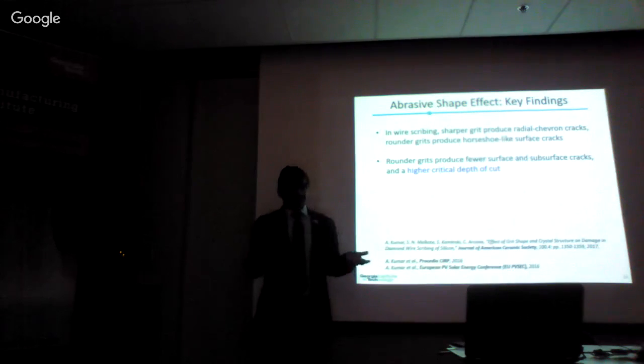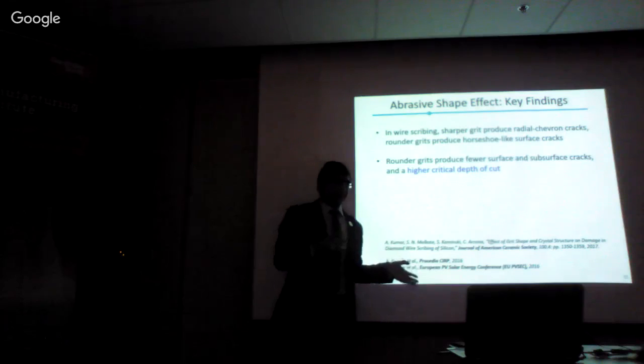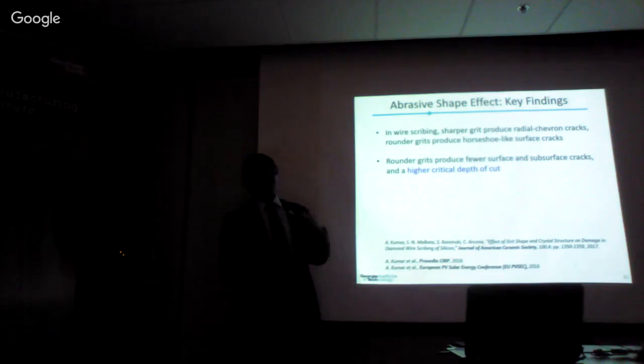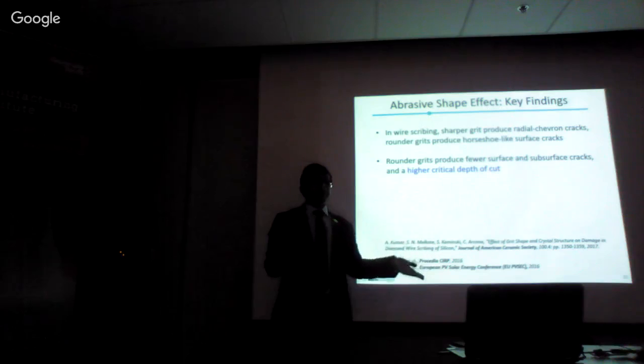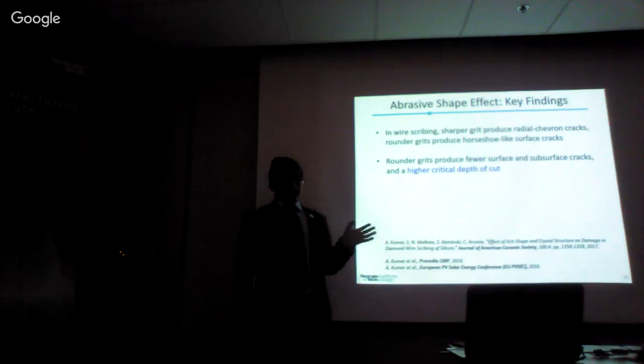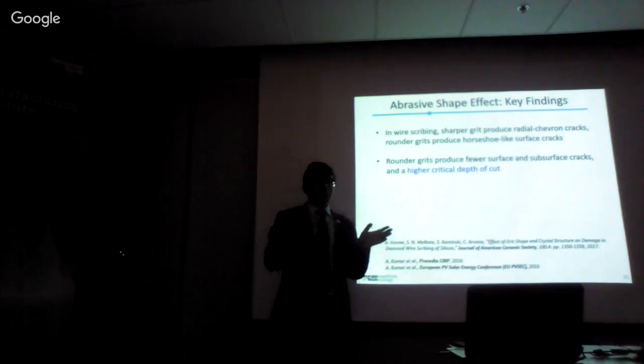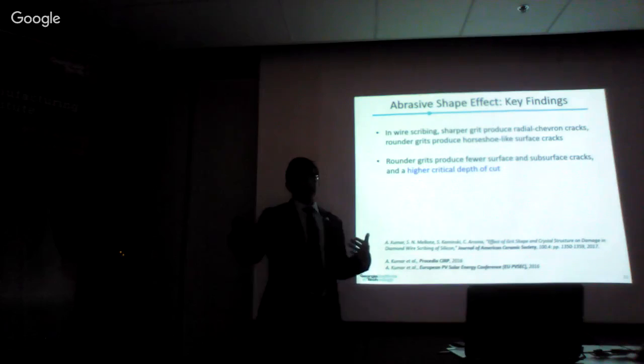So the key findings and takeaways from this task were: in wire scribing experiments, we find the sharper abrasive grit shapes produce radial chevron cracks at the sides of the groove, whereas the rounder shaped abrasives produce horseshoe-like surface cracks within the groove, and rounder abrasive grit shapes produce fewer surface and subsurface cracks overall and a higher critical depth of cut.